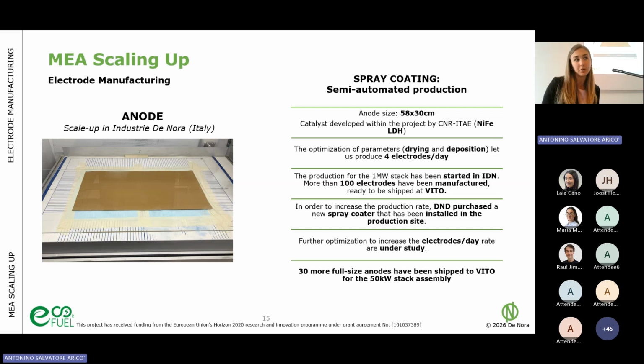In order to increase the production rate, our site in Germany, Nora Deutschland, purchased a new spray coater. So let's say we can double the production at least. But still, the production for the 1 megawatt stack has been started in IDN. More than 100 electrodes have been manufactured and are ready to be shipped. And 30 more full-size anodes have been shipped to VITO for the 50 kilowatt stack assembly. So that was regarding the anode.